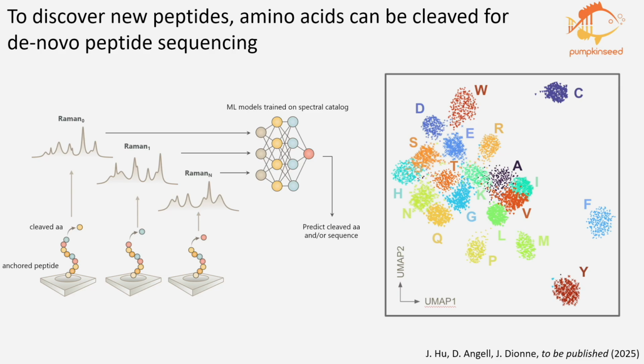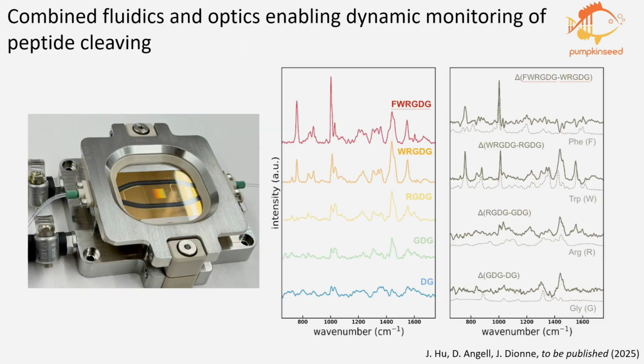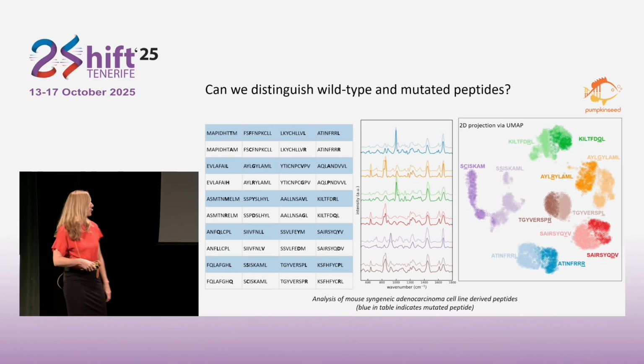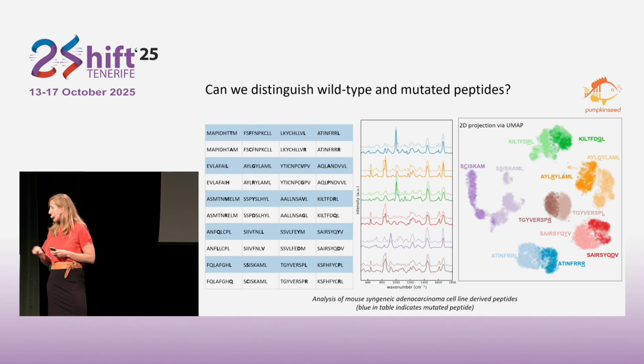So this is the company Pumpkin Seed, spun out from my lab. And as we are looking at changes in the Raman signal before cleavage, during cleavage, when a particular reagent comes in and cleaves just one amino acid residue at a time, and after, we're able to uniquely determine which amino acid has been cleaved off, at least for these immune-related peptides. So here is an example of the chip in a flow cell, where we can control the temperature and the pH and introduce different reagents for this cleavage. You can see here how the Raman spectra is changing as a function of time. And then using this process, we've been able to differentiate both wild type and mutated peptides. So here are example spectra.